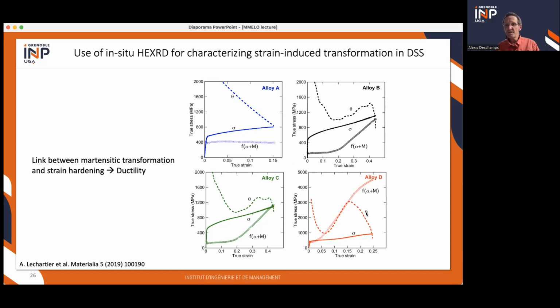When you go to alloy D, the situation is slightly better. You have a fast transformation of martensite, and so an increase of strain hardening rate exactly correlated to the fastest transformation rate. But then it's so fast that it saturates, and when it saturates, the strain hardening rate goes down to 0, and then you have the Considère criterion, and the strain becomes better but not extraordinary.